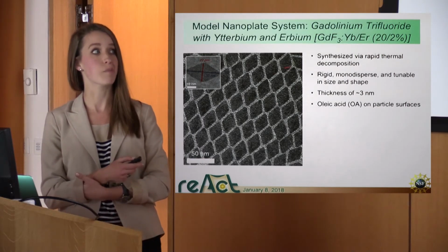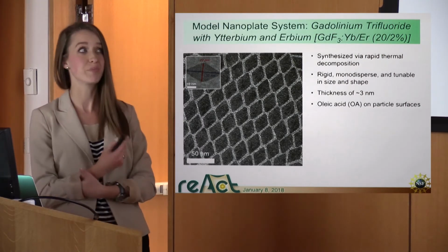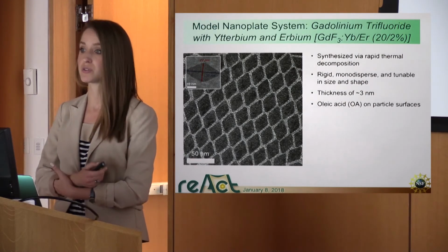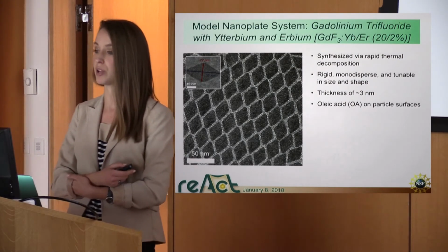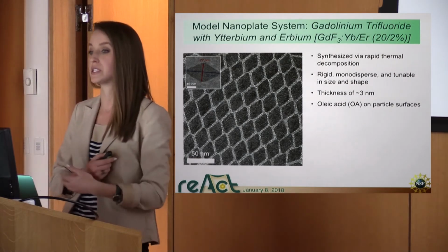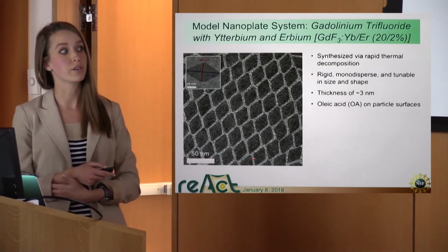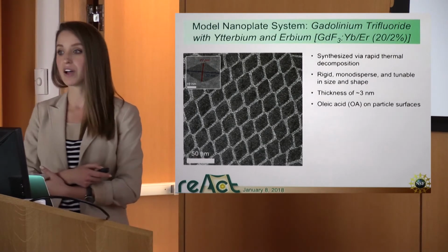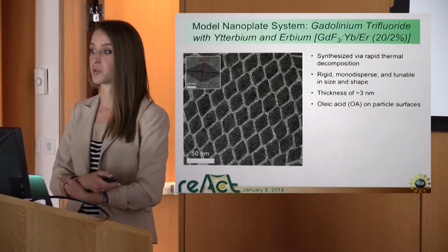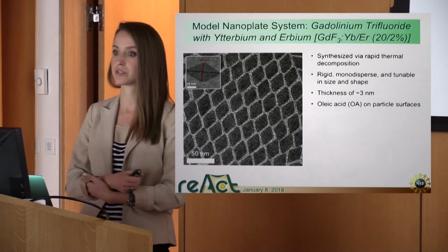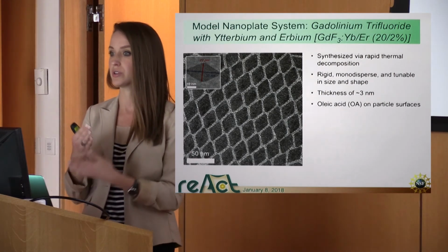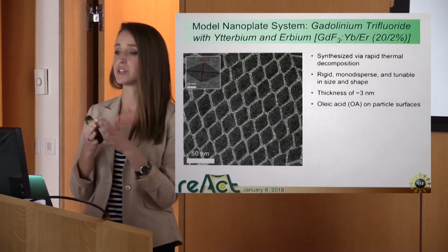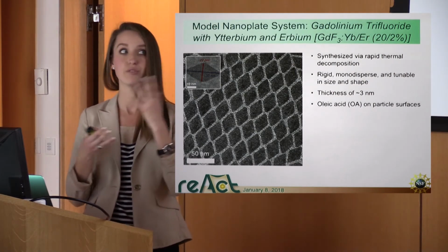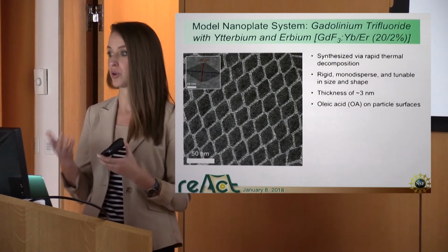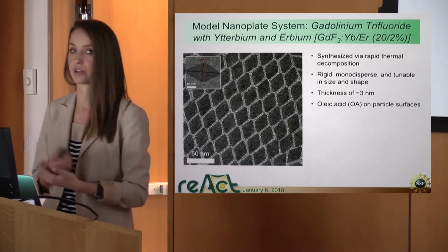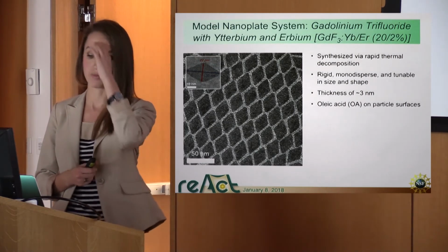But I picked this particle in this library because of the platelet shape, and also the dimensions are quite compatible with my block copolymer. The domain spacing of my block copolymer is about 18 nanometers, and I'm incorporating a particle with the longest dimension of about 35 nanometers, the shorter diagonal of about 22 nanometers, and a thickness of about 3 nanometers. When we think about incorporating a particle into a domain, we don't want to disrupt the local chain conformation and have too much of an entropic penalty. So 3 nanometer thickness is quite compatible with my domain spacing.